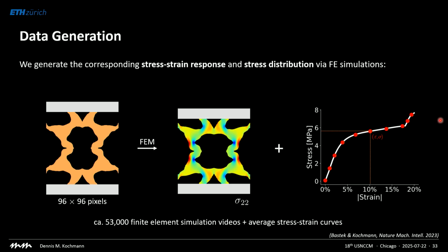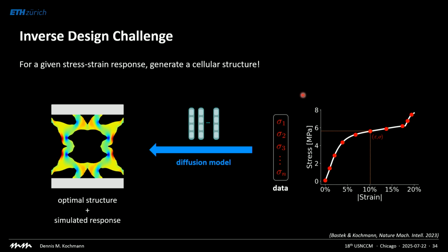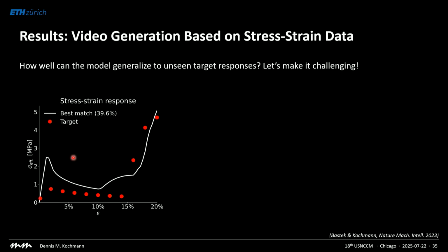What we want now is to go the other way around. To this end, we have to somehow parameterize the stress-strain curve. For example, you can pick equal strain increments and just record the stress values. And once you have these stress values, this is now my prompt. I pass this to the diffusion model, and what I want to get out is the structure on the left. That's exactly what I would like to do. So we tried this, and it turned out it works amazingly well, just with 53,000 structures.